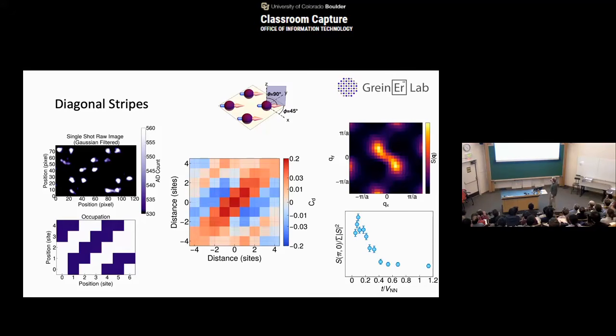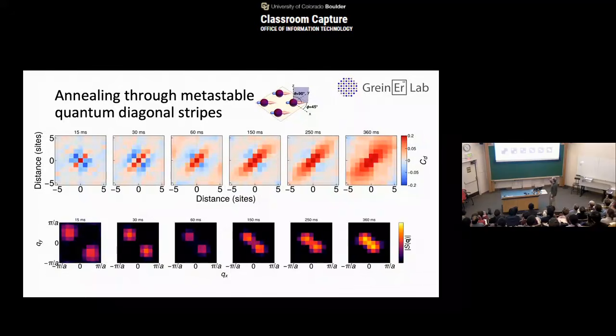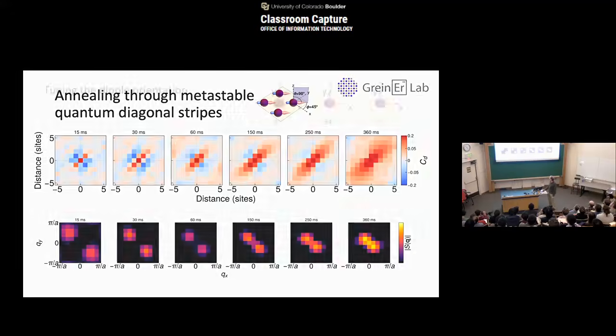If the stripes are aligned like this, it is actually not the ground state. So we tried to vary the time, and depending on how quickly we ramp, we can see different stripe spacings. In the Fourier transform, this is nicely visible, these two peaks moving closer and closer together, and ultimately, if you're adiabatic, you get the phase separation, because the particles prefer to all clump together into one oval kind of shape. That is the ground state, the phase separation, if the dipoles are completely in the plane. And so it was fun to see this and to see these metastable states, actually.